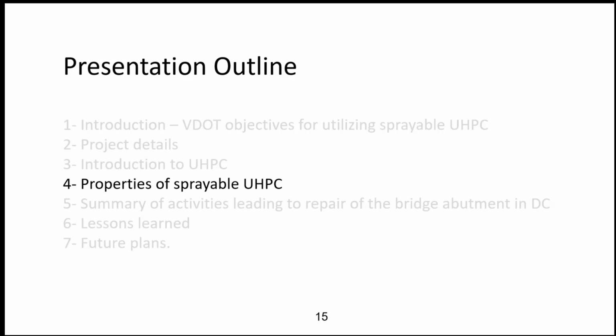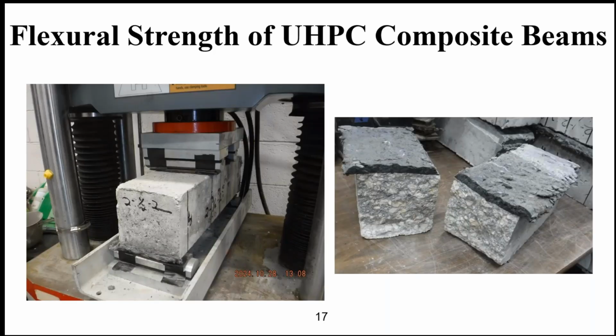and as the construction industry gains confidence, I think its application is going to increase. And one of the main reasons for the high cost of the UHPC is really the steel fibers. In 1 cubic yard of UHPC, we use about 250 pounds of steel fibers. So let me just show you some data that we have.